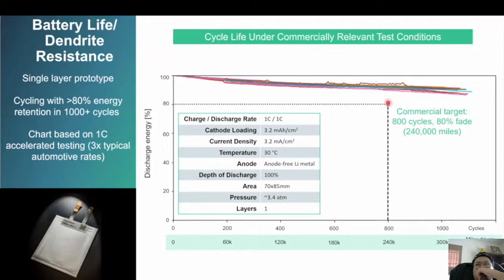The commercial target that Volkswagen has set for us and that we're setting for ourselves is 800 cycles to 80% fade. For context, typical EV warranty today would be somewhere in between 100 and 150,000 miles to 70%. So somewhere where my cursor is right here. We're trying to get to this 800 cycles to 80% target here.